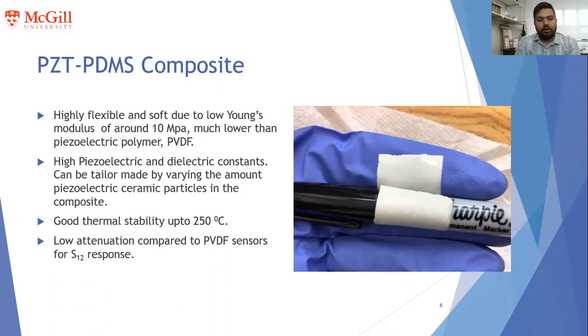Also, we have not tested it, but theoretically this composite is stable up to 250 degrees, as PDMS is thermally stable up to 250 degrees, and even PZT's Curie point is 300 degrees. We also measured the scattering parameter S12, the forward transmission response of the sensor, which gives very low attenuation, meaning low insertion loss, which is very low compared to the other popular piezoelectric polymer, PVDF.